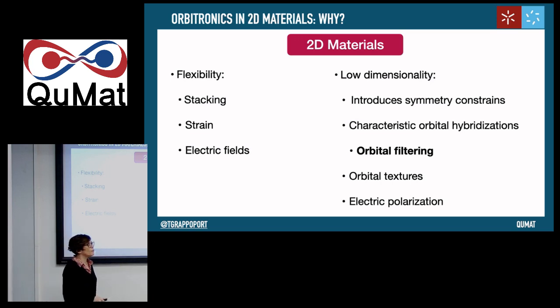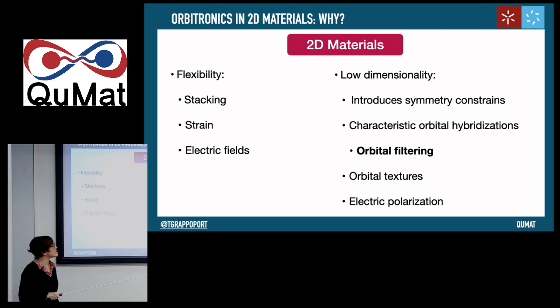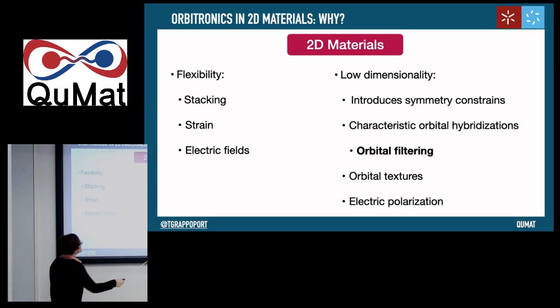An example of this is bismuthene. Depending on the substrate, you can actually shuffle p_z orbitals that were at the Fermi energy down to very low energies and promote, for example, a quantum spin Hall insulator. So we can do some orbital filtering.